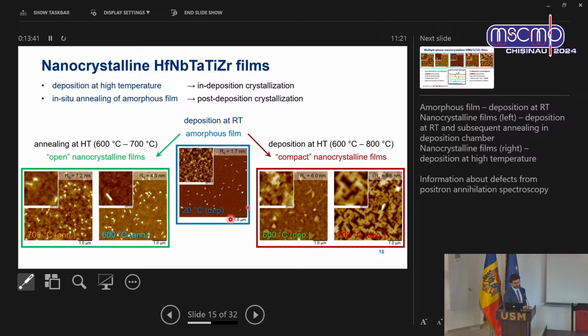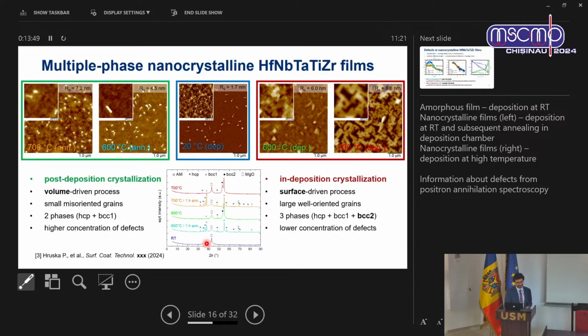The phase analysis revealed that we obviously don't have single phase films. We have a mixture in the left case of those hexagonal and cubic phase. However, the high temperature deposition also introduced some fractions of the high entropy phase. Also, on the left, the annealing gives you a higher concentration of defects, smaller grains, let's say a lower quality of the films compared to the deposition of the films at increased temperature.